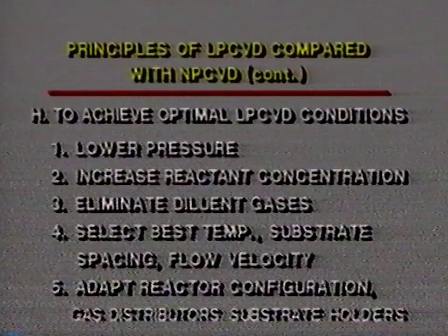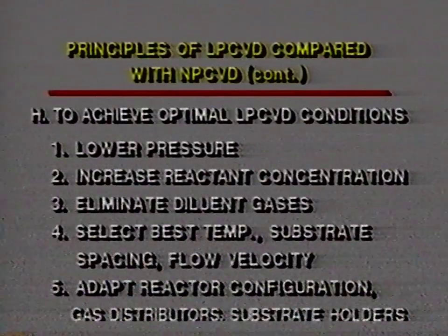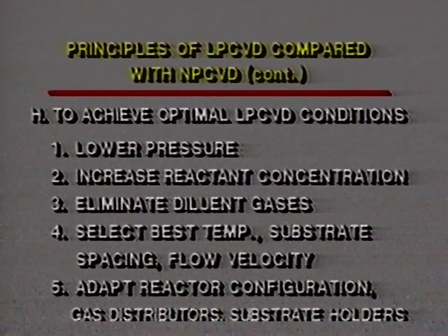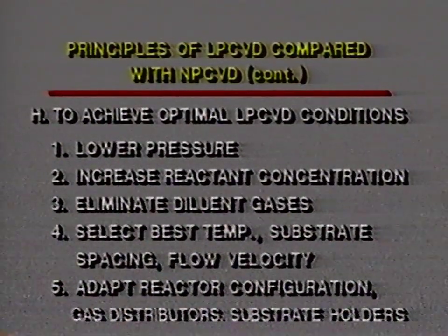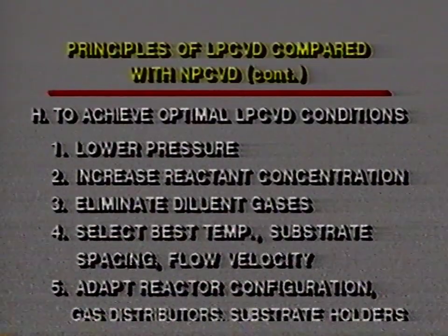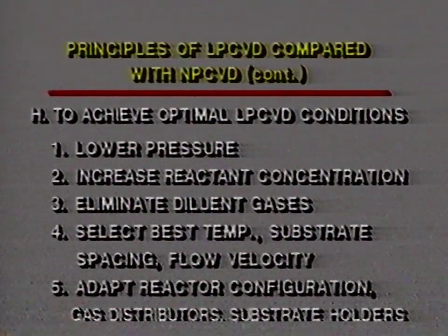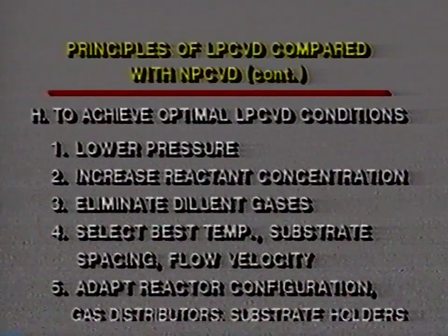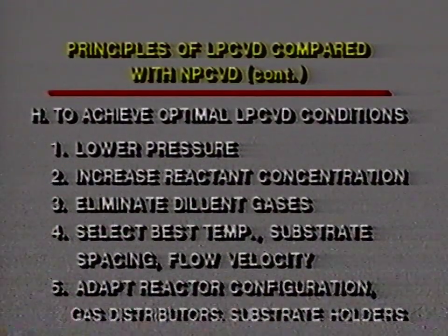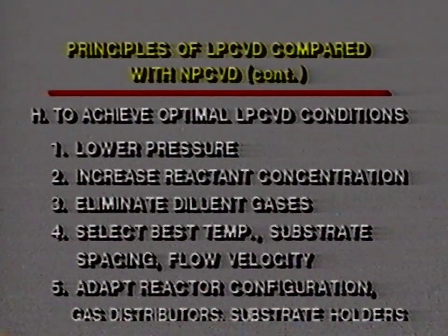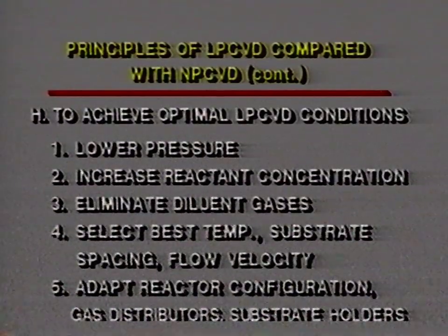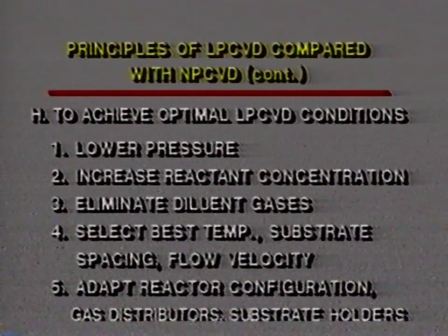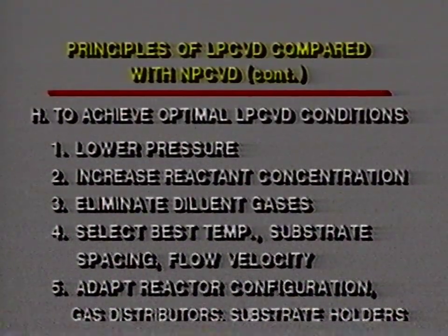Now, the substrate spacing is another important aspect. That is the wafer-to-wafer spacing and also the flow velocity. All of those factors have to be optimized to get the best film uniformity. And finally, we have to adapt the reactor configuration itself as far as gas distribution is concerned to give us the best uniformity, especially at the low temperature end. This is an important consideration where we have to distribute the gas as uniformly as we can.